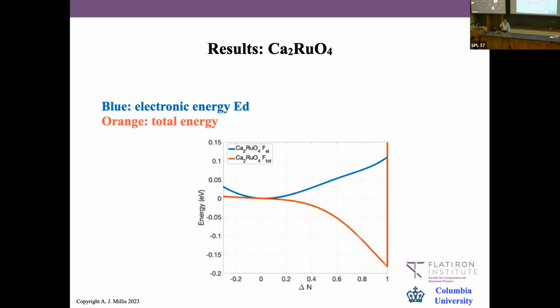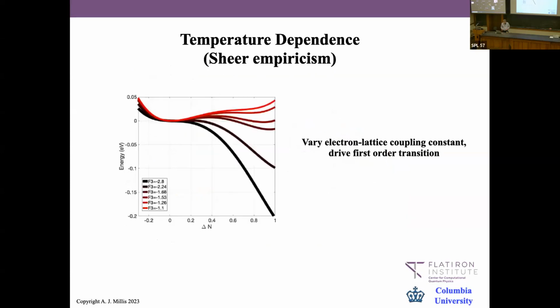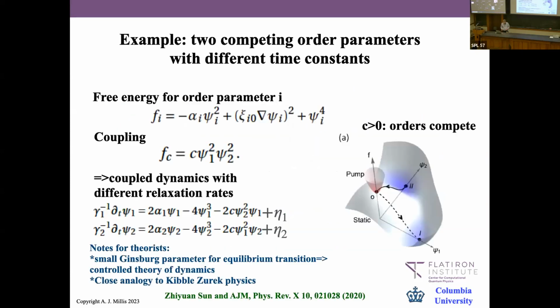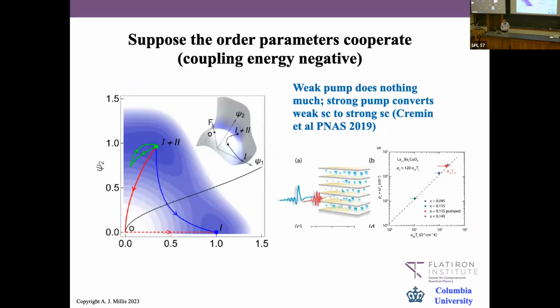Maybe there's a process. Well, but they don't help you basically, because if you liberate that much energy, then typically the Auger or inverse Auger process simply kicks another electron up, so it doesn't really change your imbalance, and then that relaxes back down. You decrease the number of electrons, but you don't take energy out of the system. That's your point. Okay. Right.